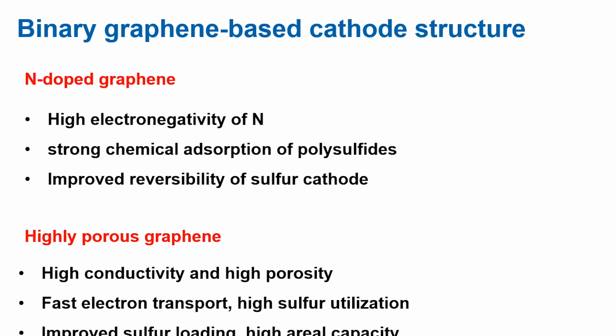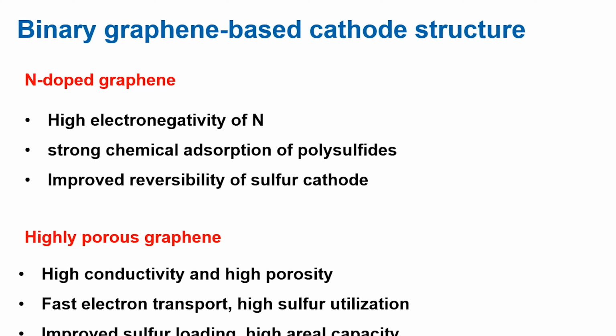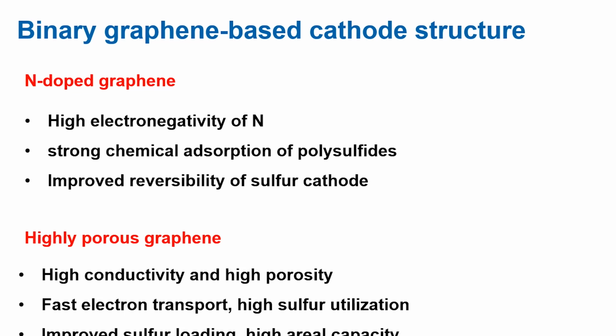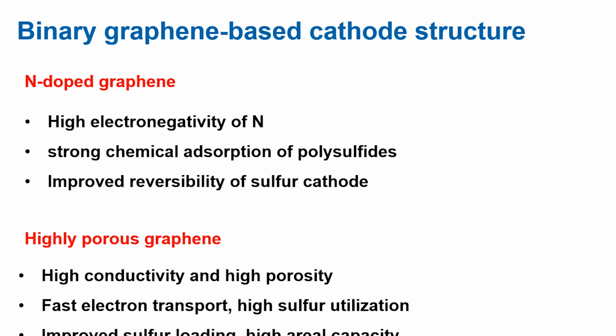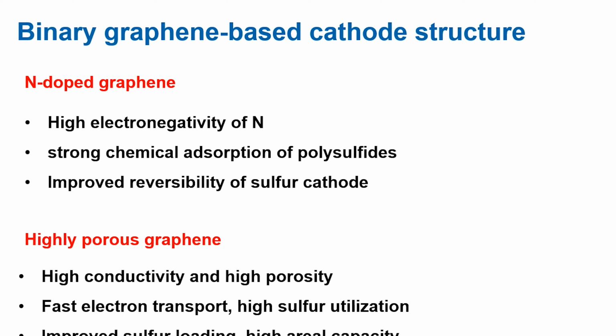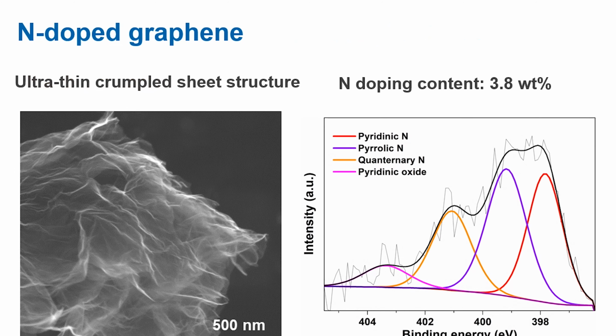The second example is about the binary graphene-based cathode structure. Here we use two kinds of graphene. First is nitrogen-doped graphene. In this case, the high electronegativity of nitrogen could enable strong chemical adsorption of polysulfides, and this will improve the reversibility of the sulfur cathode. Second is the highly porous graphene. It shows both high conductivity and high porosity to enable fast electron transport and also results in improved sulfur loading and high areal capacity.